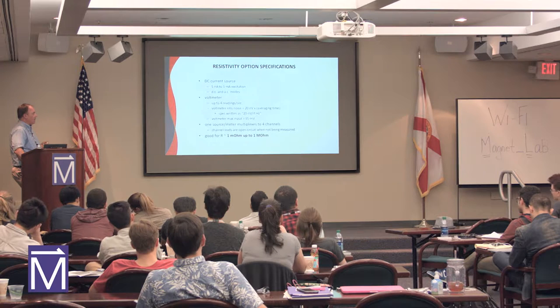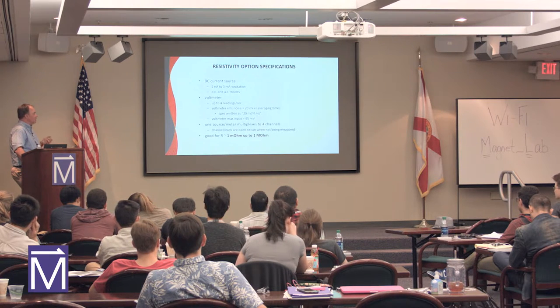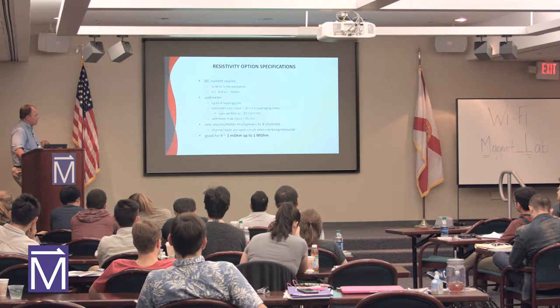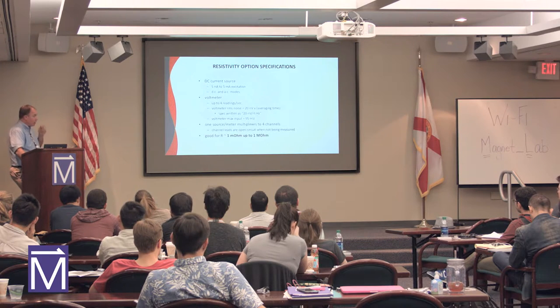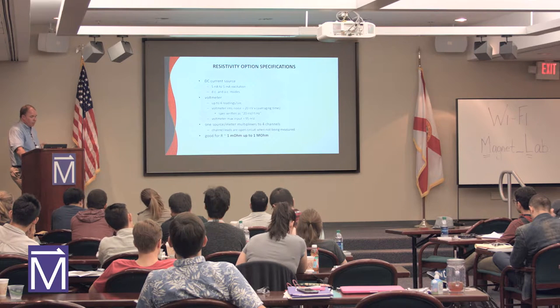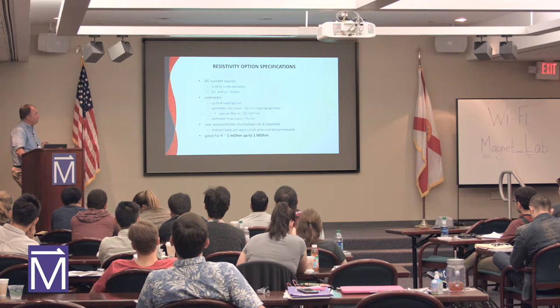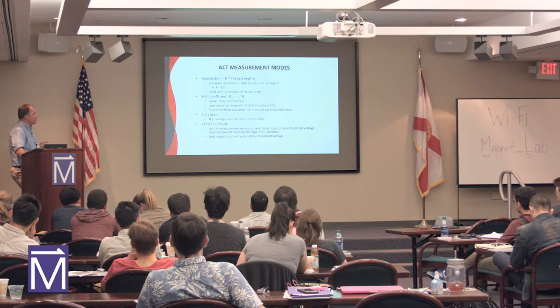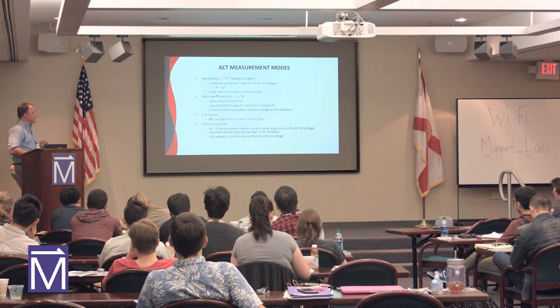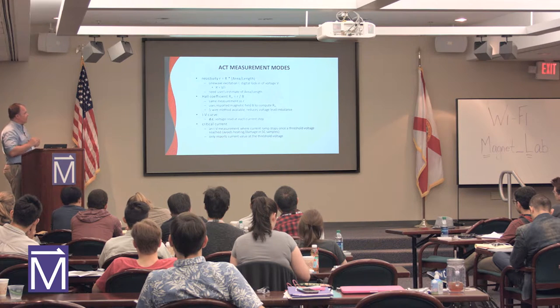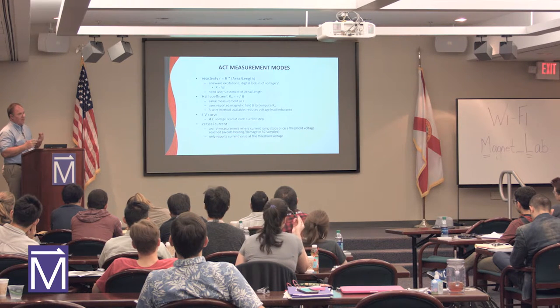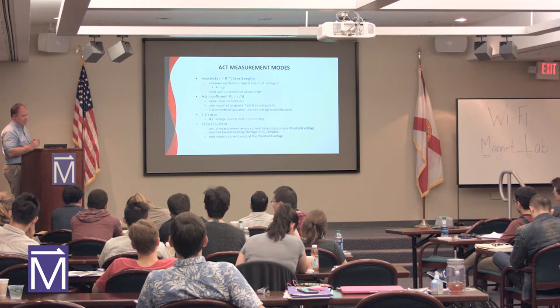5 nanoamp to 5 milliamp excitation, 4 readings a second. The bottom portion of the slide, the one to talk about, is the 1 milliohm to 1 megaohm, the good sweet spot for that measurement. ACT measurements, critical current measurements. So that's pretty much the key measurement: IV curves, Hall coefficient, and resistivity type measurements. Those are the 4 things you can get out of the ACT measurements.